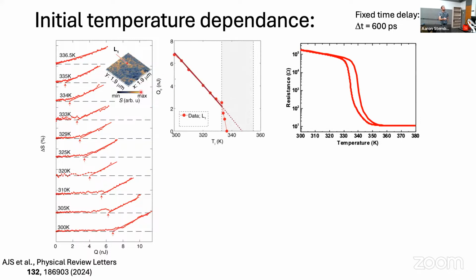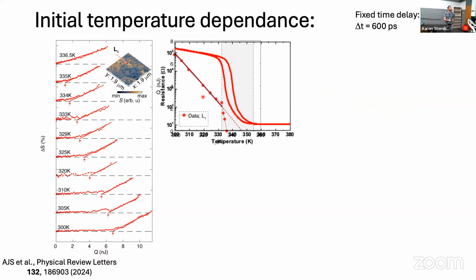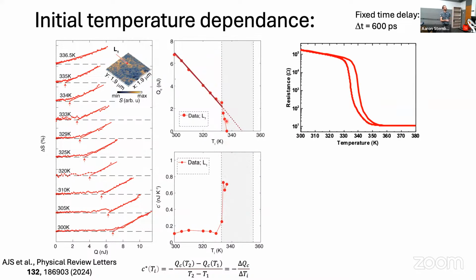And plotting this data of the fluence threshold as a function of the base temperature, we can see that this is a nice regular linear decrease until a certain temperature where the fluence threshold starts to decrease rapidly. And this can be compared with resistivity measurements on the same film. We see that this kink where the fluence threshold starts to decrease rapidly occurs around the same temperature where we observe hysteresis in the resistivity measurements. So this is around the insulator to metal transition temperature.